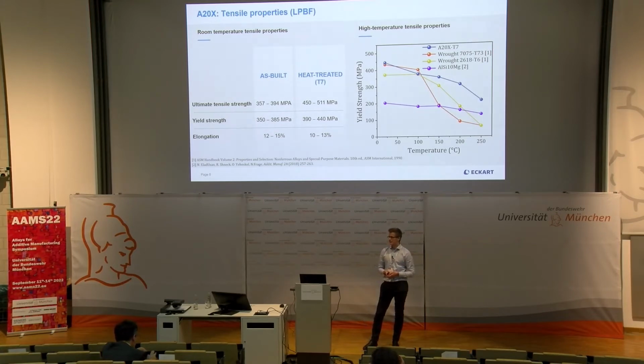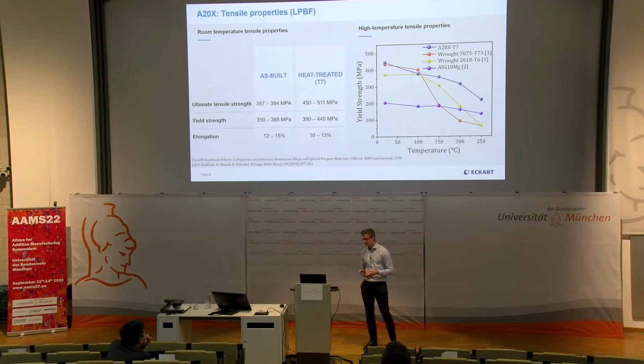And so Wrought 7075 as well as 2618, which is a high temperature aluminium copper alloy. A20X compares very favorably to these alloys, which, taken together with the good ductility, is a huge advantage as it opens up applications at 150 degrees C or higher where many other aluminium alloys cannot operate.